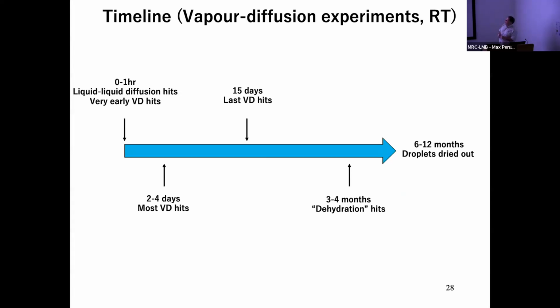in the first hour you may have liquid diffusion happening, because we don't mix the drops, they are too small to mix. So I realized that for some of them, there's first a liquid diffusion occurring in the drop, and that can actually produce heat. So you sometimes have very early heat. It's a good time as well to check for false positives which were just dropped there, for example, some salt that was not well solubilized from the reagents or things like that. There could also be very tiny contaminants, like very tiny pieces of plastic that look like crystals. So you will see that as well at the very beginning.